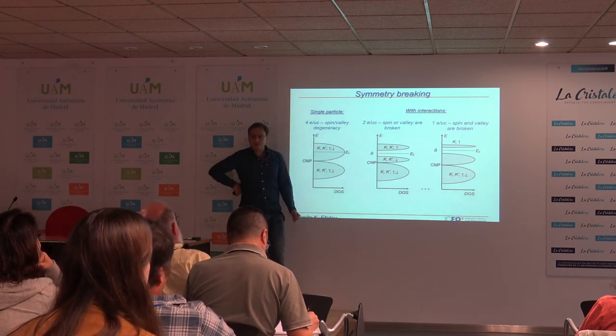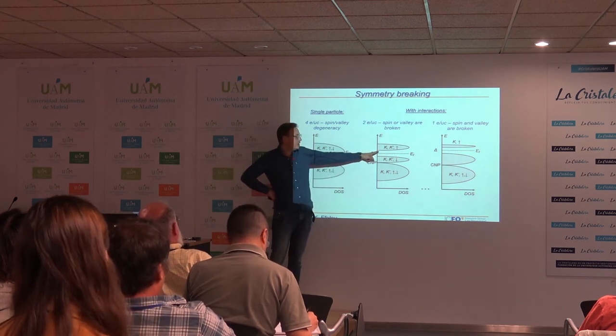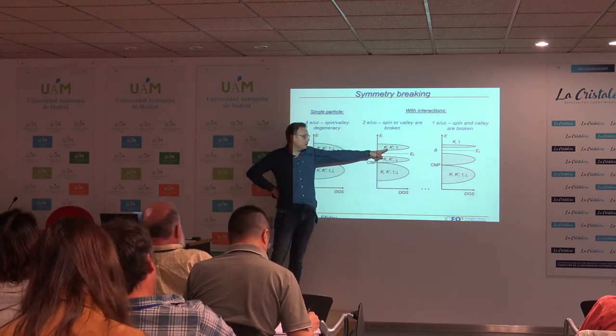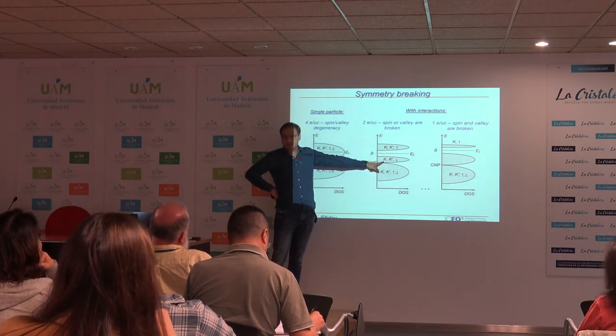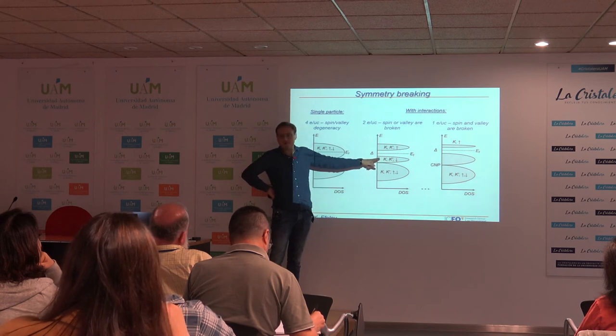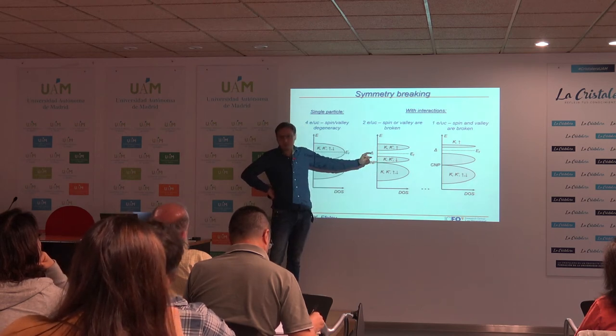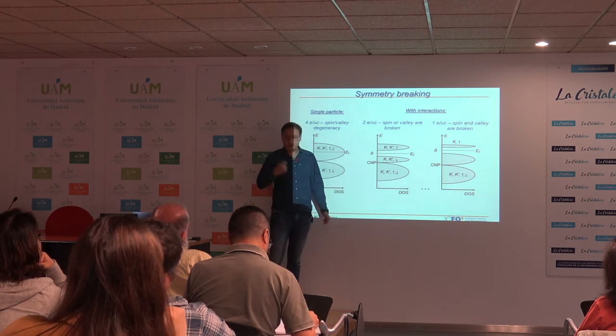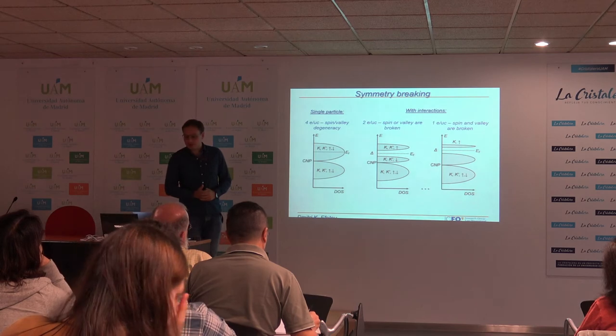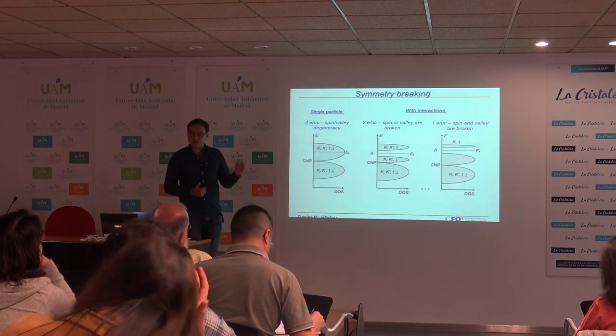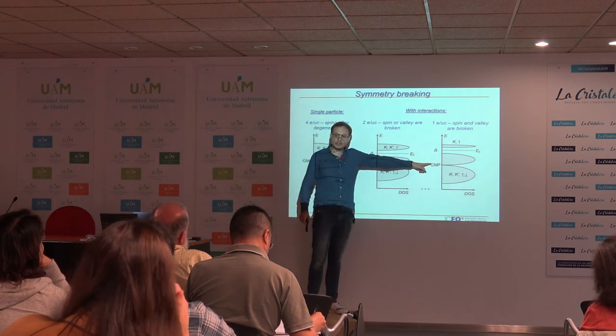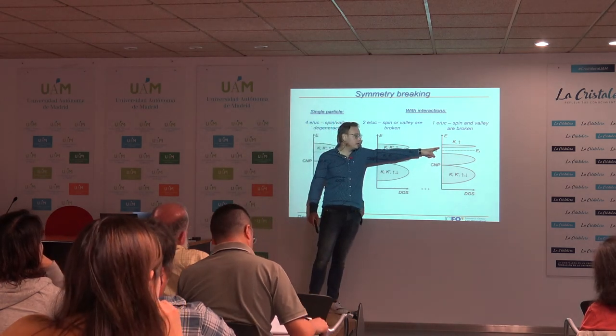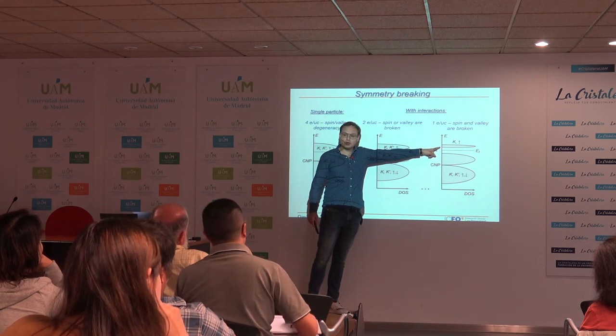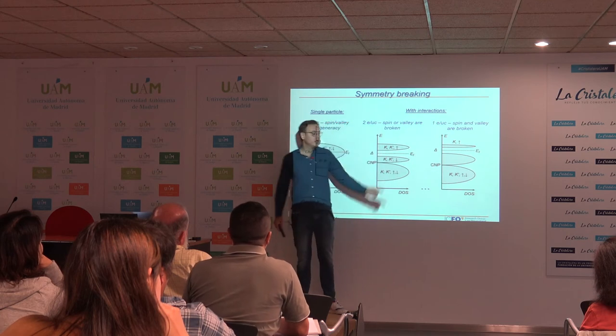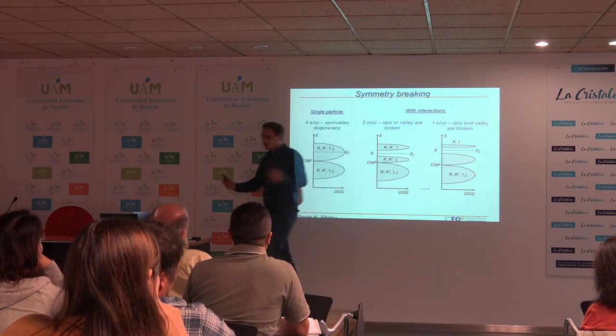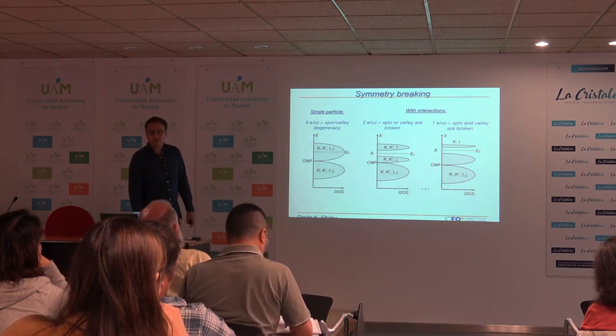So then in principle what can happen is, we don't know yet for sure, but what can happen is, for example, that the top band is spin up polarized, the bottom band is spin down polarized, right? And nothing happens to the valley degrees of freedom. So both are valley degenerate. But of course, the other thing which can happen, in the case where you have interacting gap opening at every integer filling, is that eventually you also have to consider this type of picture, where maybe the bands are fully polarized, right? So it's valley and spin polarized. And of course, in any of these configurations, you are supposed to get presumably some sort of ferromagnetic states.